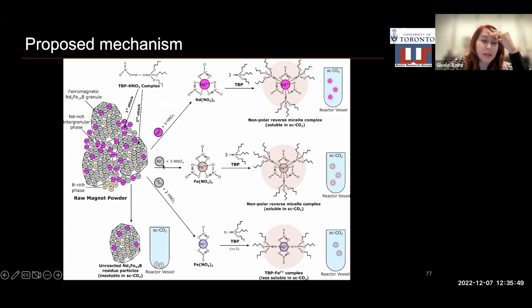Iron can form iron 3 and iron 2. Iron 3 behaves exactly like neodymium 3, so we will have iron 3 with 3 nitrate and 3 TBP molecules. But iron 2 forms iron nitrate 2, and here we hypothesize that the number of TBP molecules is 2, so iron 2 nitrate TBP2 has only 6 aliphatic chains. So iron 2 has a lower solubility in supercritical CO2 because of the reduced number of aliphatic chains.